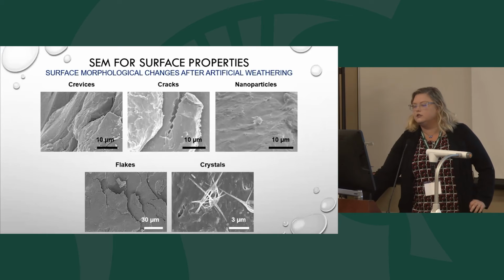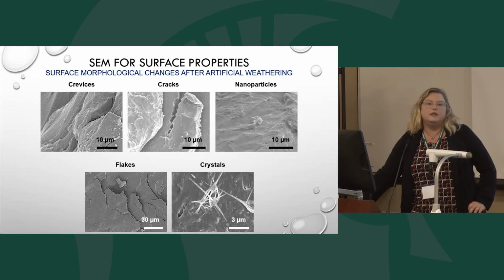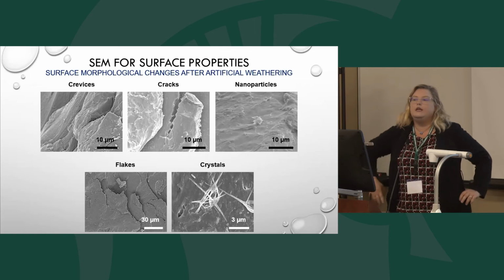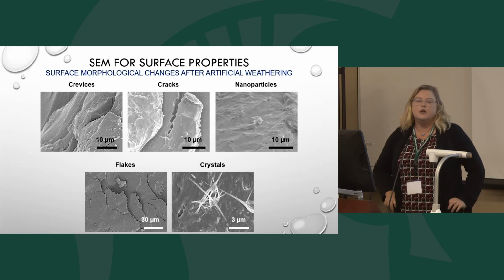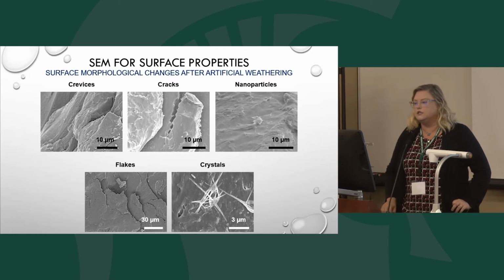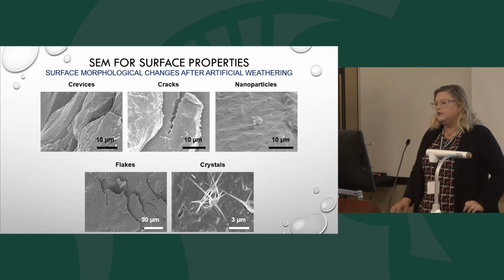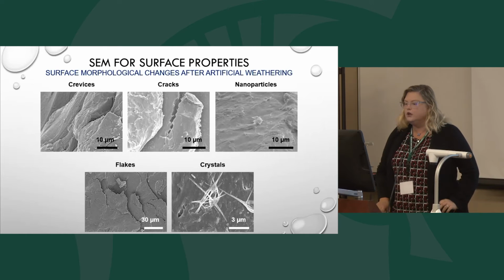And then we're seeing these crystalline surfaces either revealed or form, especially when we put them in the environmental chamber and we increase the heat, and the sun simulator lamp is on full blast to accelerate the aging process. And we see these phase changes occur.